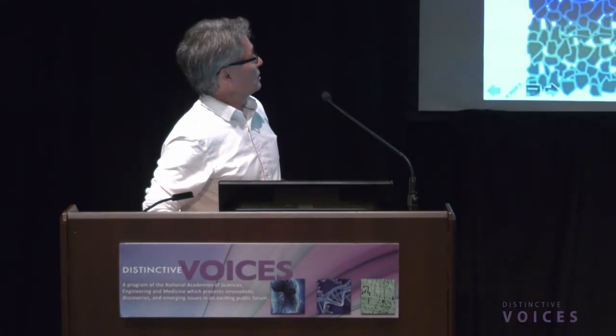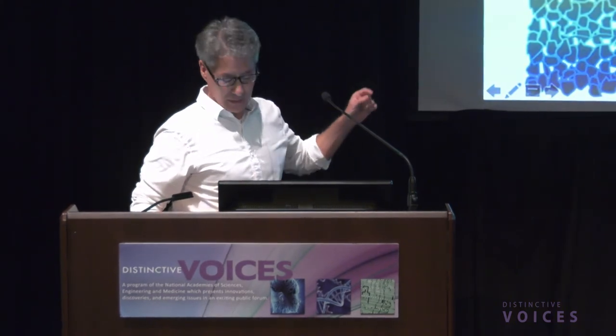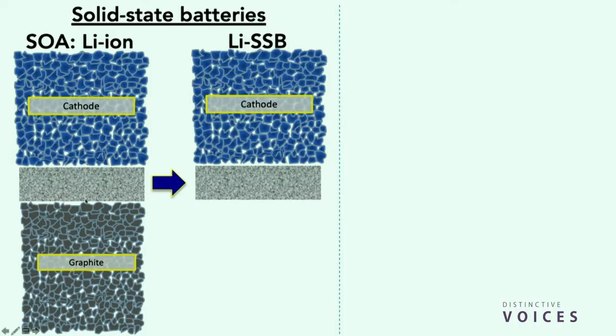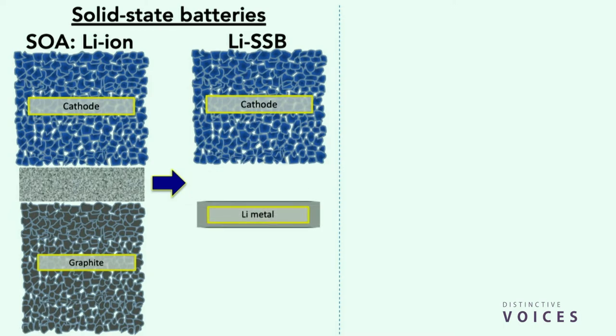So if you take a current lithium-ion battery, this is drawn to scale. Let's get rid of graphite because of the volume that it contributes, volume and mass, to the lithium-ion cell. Let's go back to lithium metal. This is, again, drawn to scale. Dramatic reduction in the volume of the lithium-ion cell. And how do we do this? Again, we put in a solid electrolyte, like a ceramic. Super hard, much harder than lithium metal. Those tree-like structures, when lithium deposits, cannot form because they're being pushed and physically squashed on the solid electrolyte.